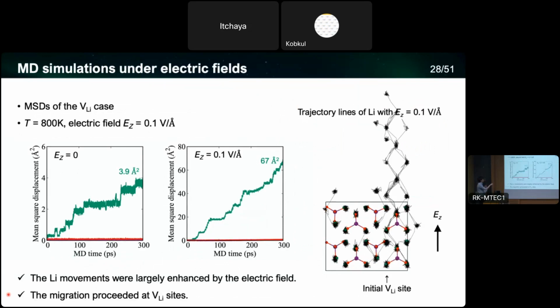So this one is without electric field, same as the previous slide. And this one is the mean square displacement under the electric field, where the electric field size is quite large, but we chose this value to enhance the motion, or to investigate within a short time period compared to the real time scale. So comparing these two, without electric field, the MSD reached around 4 angstroms squared at 300 picoseconds, but it reached around 70 angstroms squared, which is one order higher, with the electric field. And the right-hand GIF shows the lithium trajectories under the electric field.